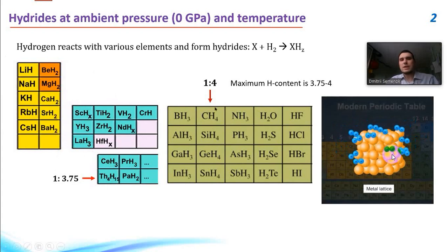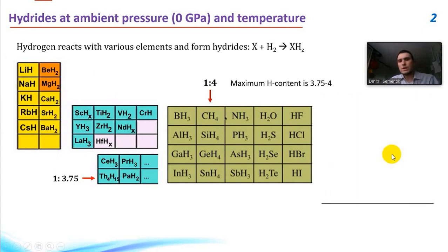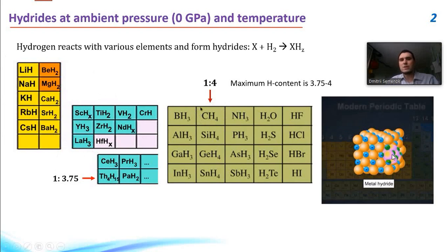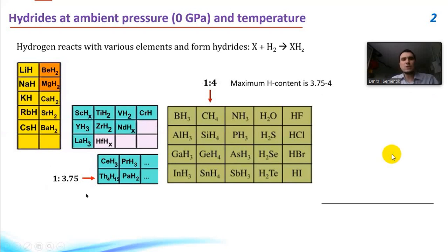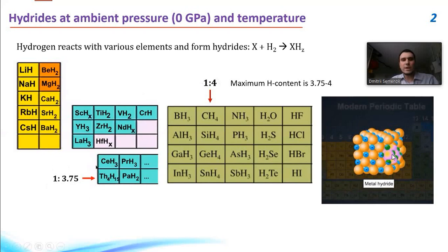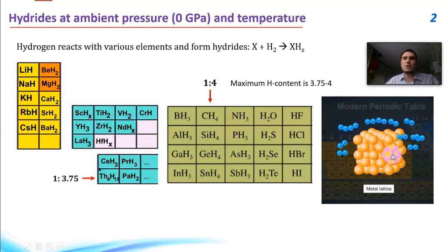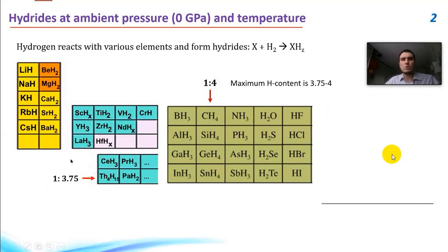The most important hydride is CH4. It's methane. It's a very stable compound with the highest hydrogen content. Its composition of atoms is 1 to 4. And among metals, the maximum hydrogen content is in thorium ThH4... Th4H15. It's also a superconductor, but at low temperature. Tc is close to 8 kelvins. But anyway, the hydrogen content is also close to 4.